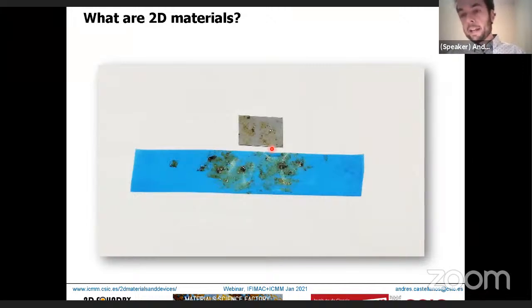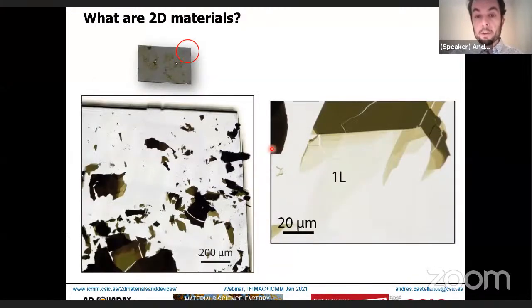Now, the problem with mechanical exfoliation is that you cannot control the position of the flakes that you transfer. You cannot control the thickness of the flakes that you transfer. So you need a technique to quickly scan the surface of your substrate and find the two-dimensional crystals you want to work with. Optical microscopy is a quite common method used to quickly scan through the surface of the substrate and find the two-dimensional material flakes.